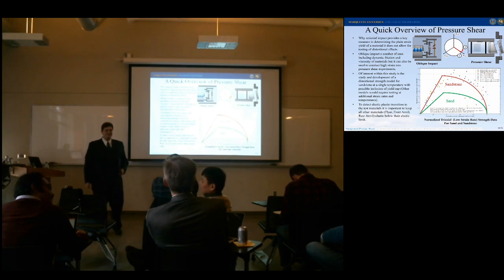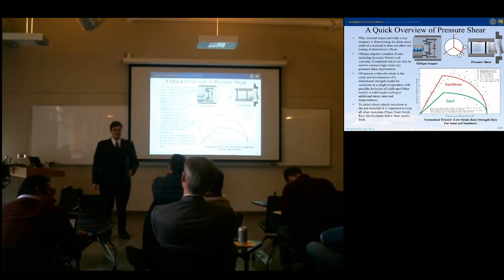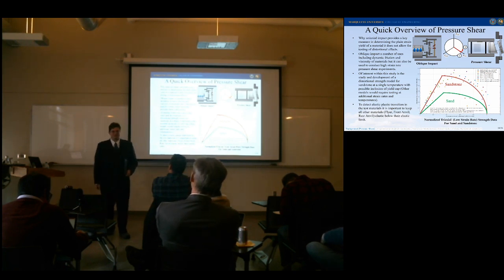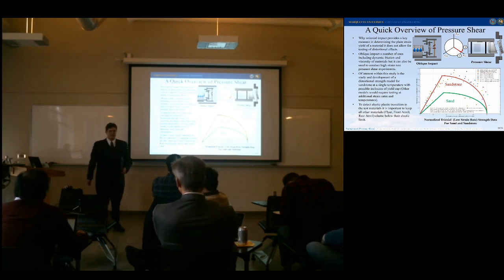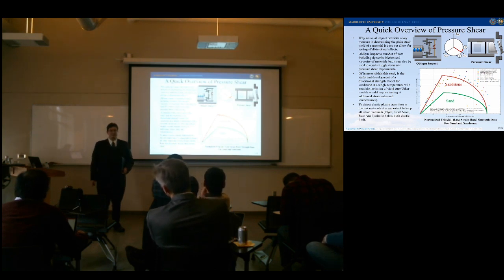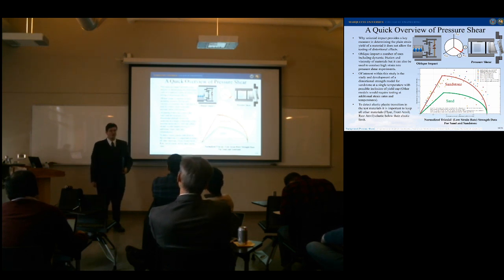How are you proposing to make your measurements? Using velocity probes. I'm measuring off the back surface the different types of waves that come through the material. I measure the amount of time that it takes the wave to travel from the front anvil to the rear anvil. That'll give me US. And then if I measure off of the rear surface, then I'll get my UP value. And for pressure shear, I'll need at least 2 probes, one to measure in the normal direction and one to measure in the shear direction.